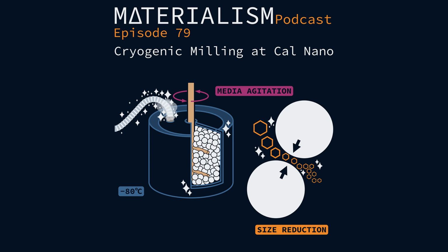And then the other thing I wanted to mention is what we've seen when doing our cryo milling, though I can't speak to exactly how it affects different milling processes. We actually do a powder coating that goes on the media and the shaft of the mill. We do what's called a break-in run, which coats everything. We remove that, then we put in our actual powder that we want to mill. Whenever something breaks off, it's just a coating of that actual material. Oh, how clever. So anything breaking off is just the break-in material, at least the same chemistry. Yeah, a very similar chemistry, which really minimizes your amount of contamination.